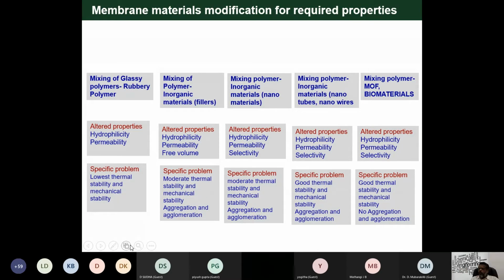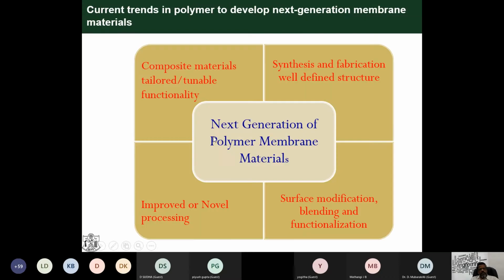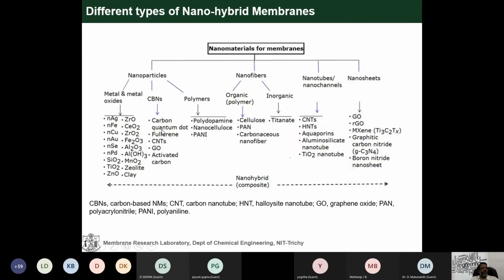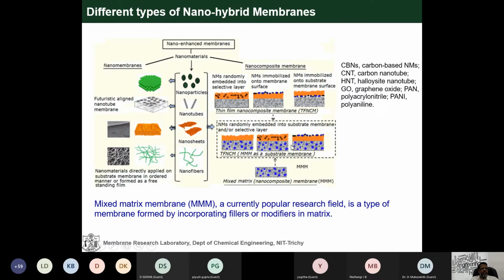Now, the recent research coming up is MOF, covalent organic framework, metal organic framework, and mixing of polymer and biomaterials, for example aquaporin or any kind of collagens. So now hydrophilicity, permeability, and selectivity improve, and it is reported there is no agglomeration, but good distribution in the polymer matrix. For that, the next generation membrane materials are synthesized with surface modification, improved novel processing, and composite materials. These are different types of nanohybrid membrane materials applicable for different combinations of organic and inorganic sheets.